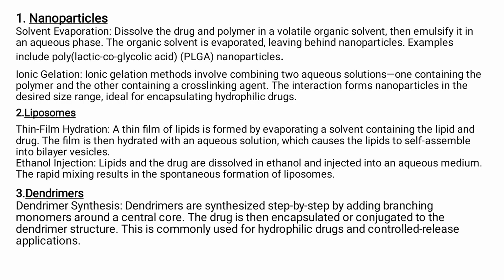Nanoparticles: various methods like the solvent evaporation method are used for nanoparticles. In that, first we have to dissolve the drug and polymer in a volatile organic solvent. Then we emulsify it in an aqueous phase. The organic solvent is evaporated, leaving behind the nanoparticles.